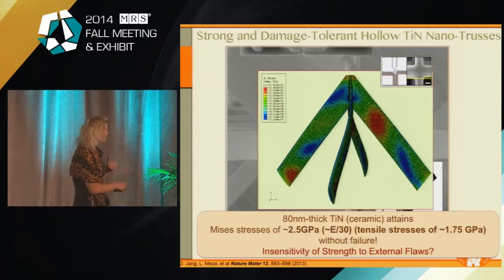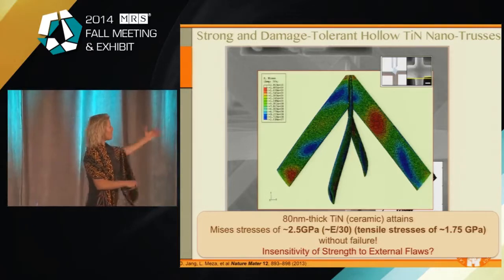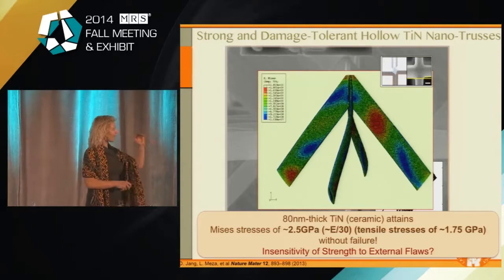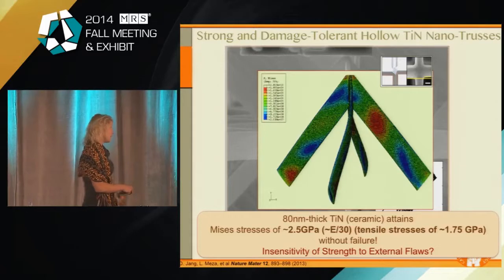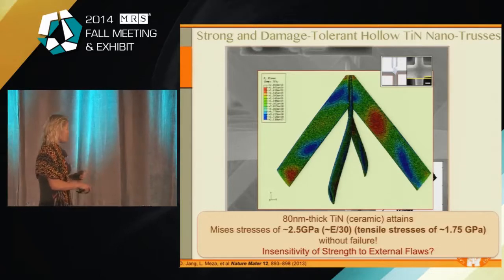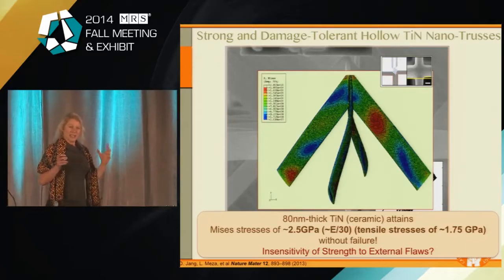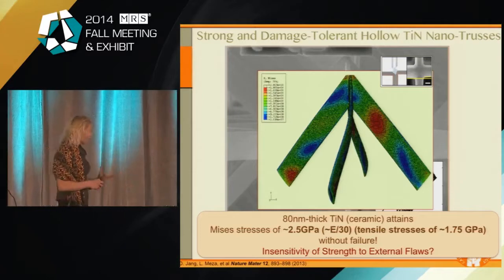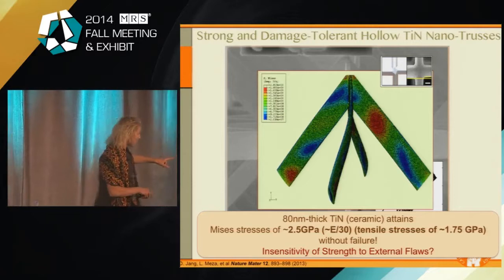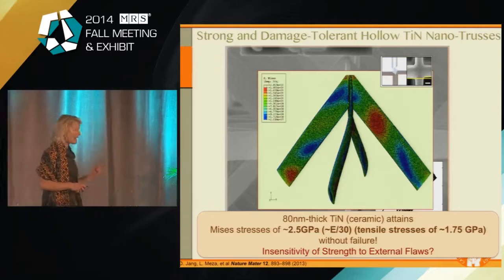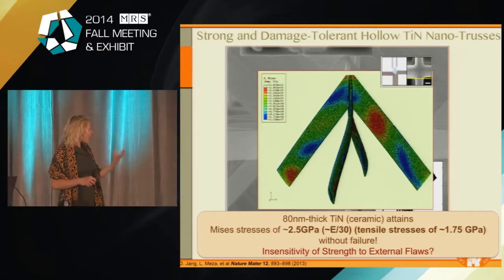So that torque, because of this imperfection, generates a bending moment with each of the beams deflecting out of the way. My student Lucas did these calculations, and you can see the Mises equivalent stress and strain distribution within these beam members. The point of the maximum deflection, of course, also corresponds to the point of the maximum Mises stress, which he calculated to be about 2.5 GPa. That's very high. That's a very, very high stress for a ceramic to be experiencing without breaking. If you convert it to a tensile stress, it's at about 1.75 GPa. So this is a fraction, maybe 1/30th of the modulus.